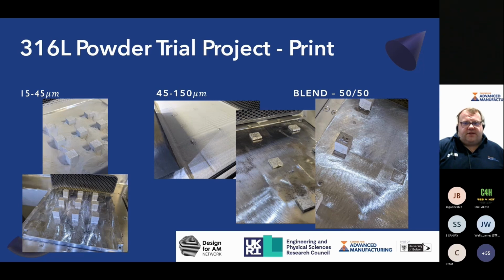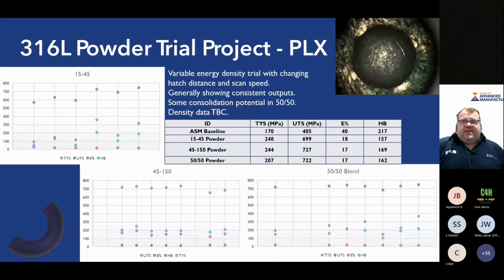the 15 to 45 on the left. The 45 to 150, we had some issues with the support parameters, so we ended up going down the route of printing a column at a time just to stop us having distortions in the powder bed. And then we went through the process of creating a quick baseline.